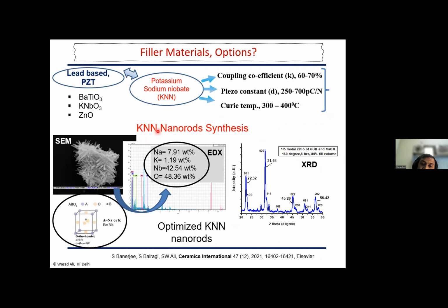So in our research, we have taken one ceramic material, which is nothing but sodium potassium niobate, which is excellent in piezoelectric characteristics. There are many materials, of course, lead-based materials. For example, PZT is very famous in terms of piezoelectric property, but this material is already banned in the European markets, and even in India, maybe it is going to be phased out because of the lead content, which is very toxic in nature. So people are looking for some lead-free material, of course, and we have synthesized a new material, new structure,